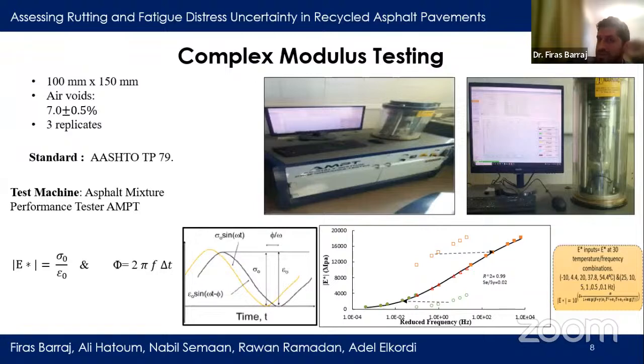So what is the complex modulus testing? Complex modulus testing consists of an application of a uniaxial compressive sinusoidal stress to an asphalt concrete sample and determining the response strain in order to compute the dynamic modulus and phase angle. The test is conducted at different temperature and frequency combinations to cover the full behavior of the material. Then the measured values are used to develop dynamic modulus master curves using the time-temperature superposition principle.